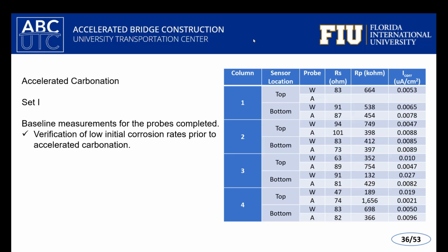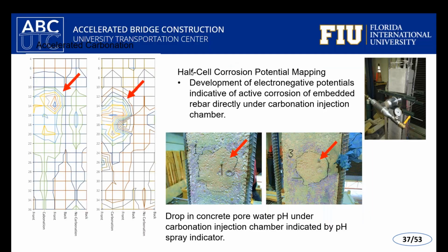Polarization resistance is inversely related to the corrosion rate. And knowing the surface area of the steel probes that we have, we can calculate the corrosion current density for each one of our samples. And notably, they're very, very small. As we indicated, again, steel loves to be in concrete. It is a very beneficial environment where it should be durable until bad things happen, including having long-term presence of carbon dioxide in the system. So the big thing about this really, we're checking our sanity, identifying the initial cases that they weren't corroding, and then we pressurize the vessel.